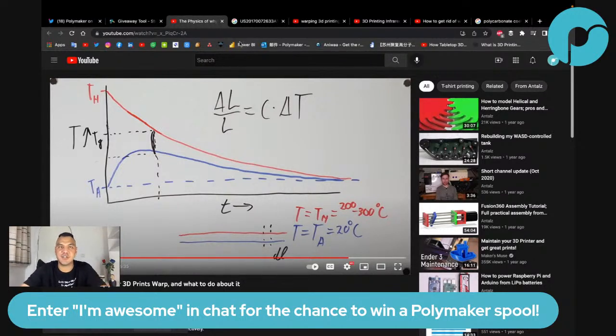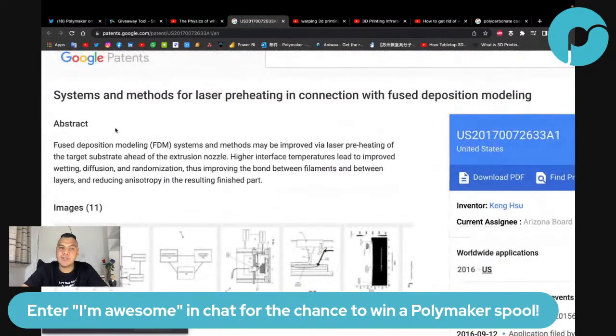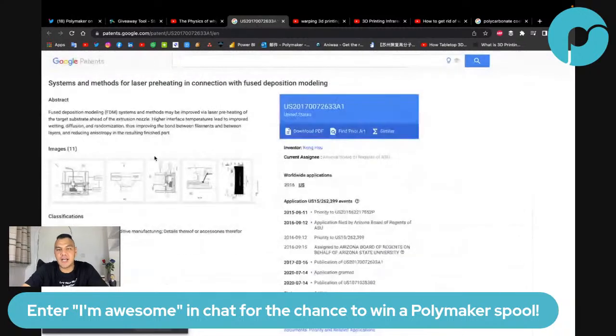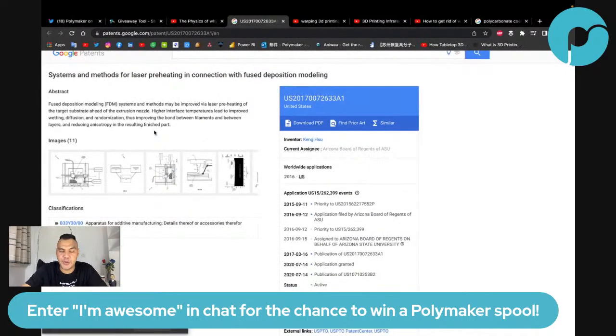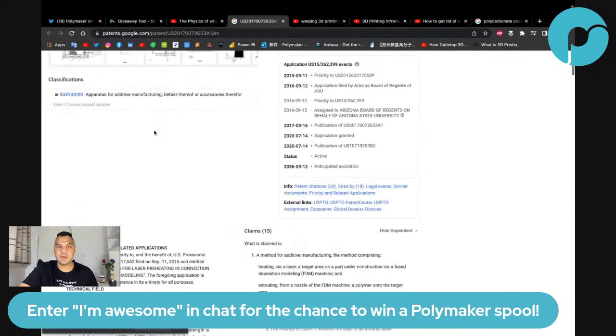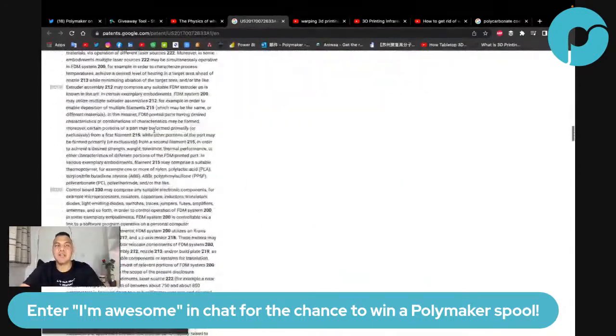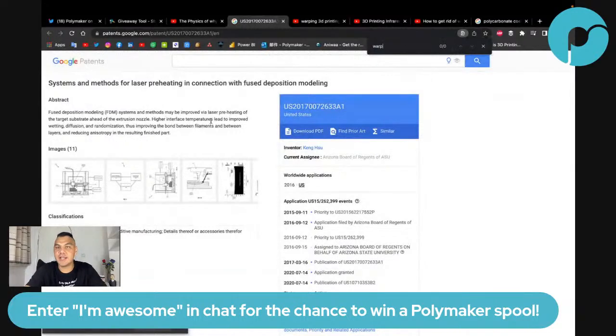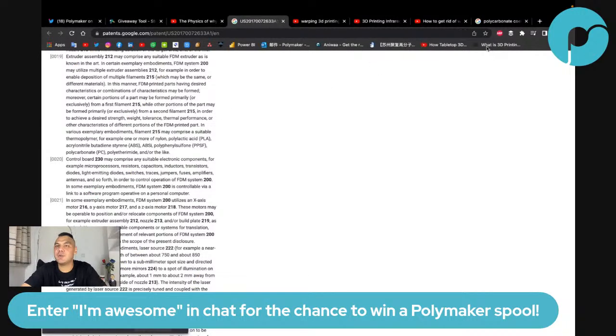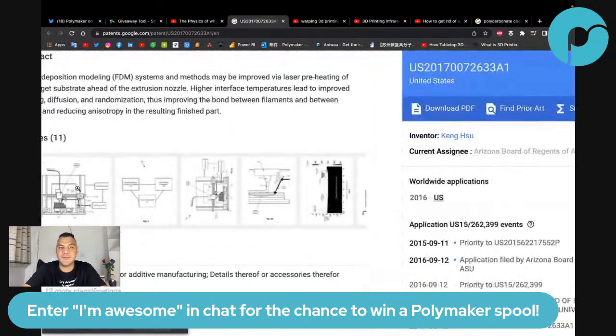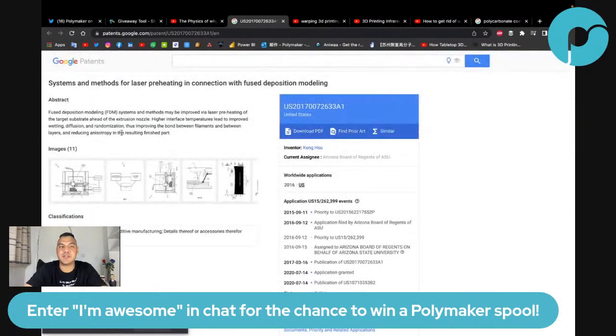If you go back to the explanation, this patent has only one purpose, or at least from what I read, I didn't read the whole thing, right? But the patent's purpose is layer adhesion. Not warping, layer adhesion. I read quickly, I read diagonally, and it's about layer adhesion. You see, I can check for warping or warp or something. There's nothing about warping because that was not their goal. So this is because of layer adhesion, and I agree with him. I agree that if you have both at a high temperature, and then I will explain how to increase the layer adhesion, and this is a great way, but nothing to do with warping.